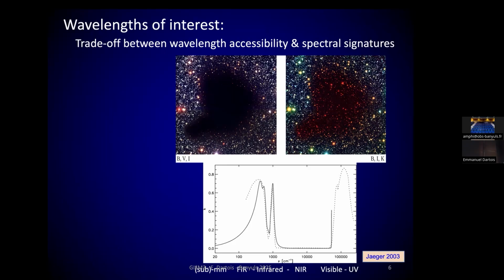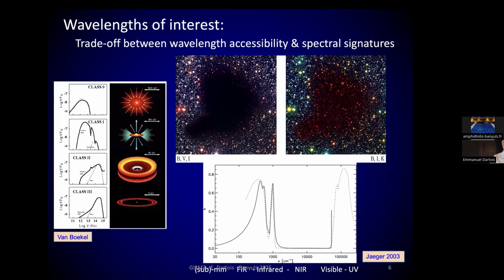With respect to solids, I show here a typical spectrum of a silicate from the sub-millimeter to the visible, and you see the absorption part of the optical indexes. So basically here you have strong signatures in the infrared, then almost nothing in the visible, and again in the UV. Which means that if we had no observation in the infrared for many of these solids, we wouldn't know what their composition is. And so it's a very crucial element, this wavelength range, in addition to the other ranges, but this is really a crucial one.